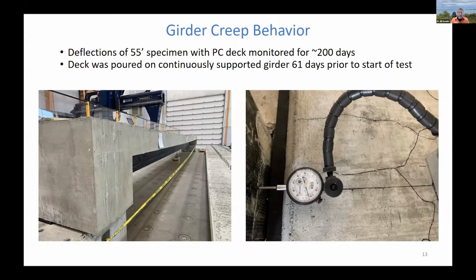It's a bit of an unknown with the FRP girder because it's got a concrete deck, and FRP itself is subject to some creep deformation, not maybe as much as concrete, but it's not creep free like steel is at normal operating temperatures where we don't really worry about creep. So to assess this, we had a specimen built 55 foot long. It actually had a full depth precast deck on it. This was a very substantial deck thickness as well. That's shown here in the lower left.